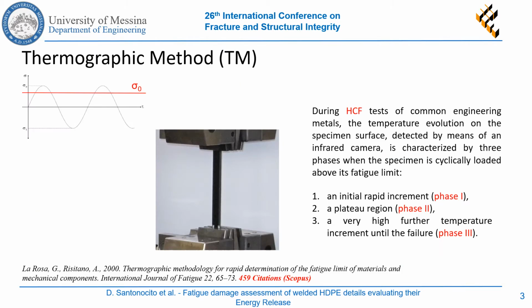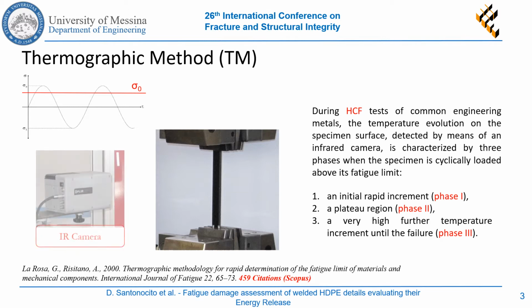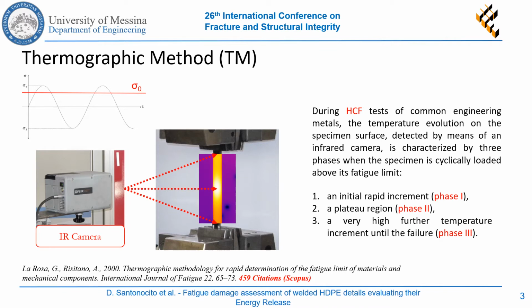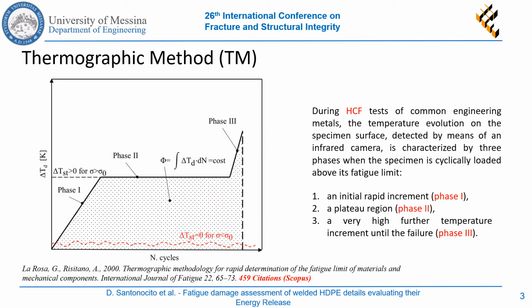Thermography has been used as an aid for assessing the fatigue properties of several kinds of materials. As observed by La Rosa and Risitano, if we cyclically test a material with a stress above its fatigue limit, the temperature evolution of the specimens monitored with an infrared camera is characterized by three phases. An initial rapid increment in the first phase, then it reaches a stabilization temperature, and finally, in the third phase, a very high further temperature increment until failure.